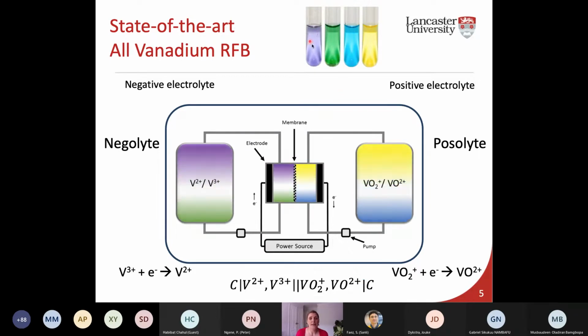Vanadium is unique in that we've got four oxidation states that are stable in acid solutions. So you've got 2, 3, 4, and 5 that are all stable species to a relatively high concentration, around 2 molar, in sulfuric acid, especially if you have additives and so on, which they do nowadays. In our negative solution, we're going to oscillate between the vanadium 2 and vanadium 3 species. That's our relatively more negative solution. On the positive side, we're seeing an oscillation between the vanadium 4 and vanadium 5 species. This is what I mean about them not being really reversible systems. This is not an electrochemically reversible couple, but in terms of how it works in a flow battery, it's considered a reversible system.